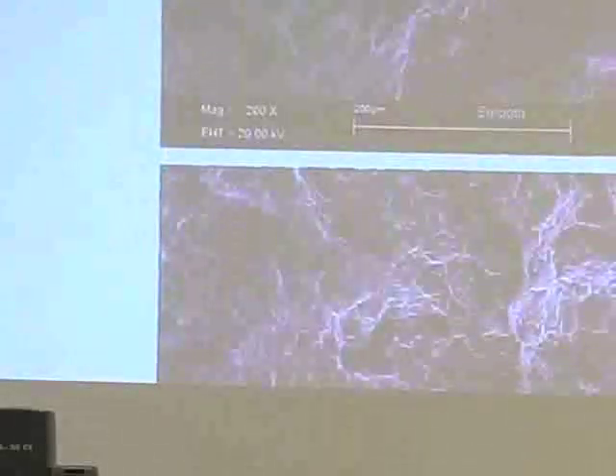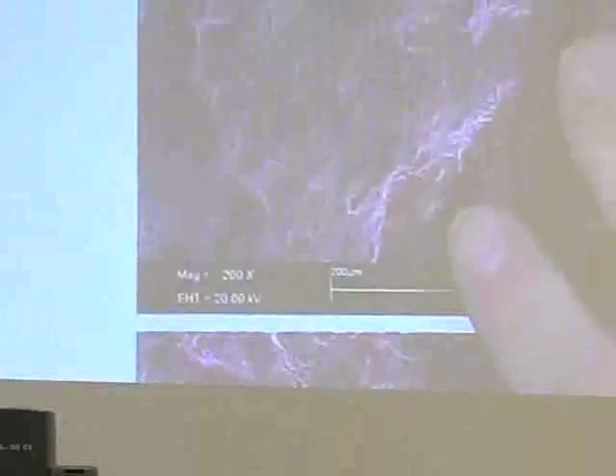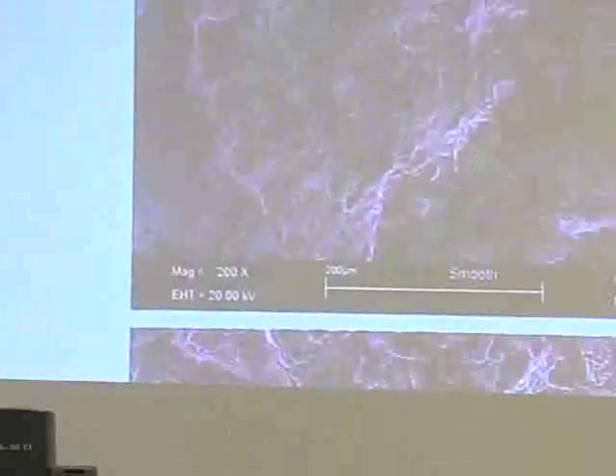so let's see if I can get this to show up. This is the unnotched tensile bar fracture in the scanning electron microscope. It is ductile dimples. It's not the greatest ductile dimples, it's a medium carbon steel, but it has ductile dimples, okay? That exact same steel, we've done nothing to it other than change the geometry of the tensile specimen by putting a notch in, at the same magnification. All of a sudden it goes from ductile dimples to cleavage fracture.